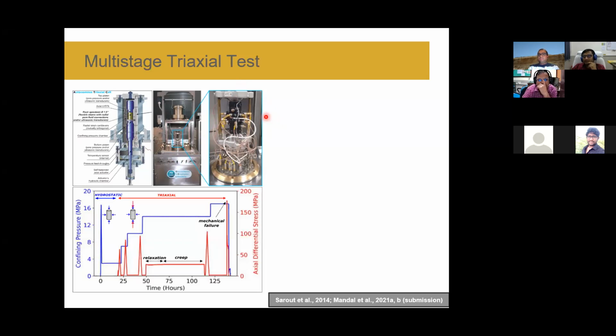And at the same time, we are able to measure the ultrasonic response, or the P and S wave response. We have the feasibility to put 20 sensors across the sample as well as at the top and bottom of the sample, so that we can look at some of the microstructural changes utilizing these ultrasonic data as well as rock physics modeling. So below is showing how the experiment has been done.